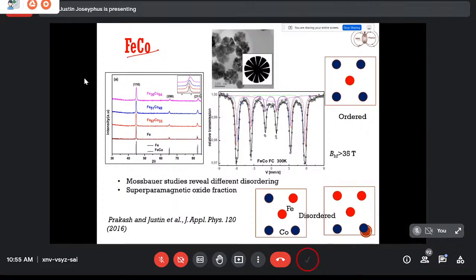And you see here, this is the X-ray diffraction pattern. XRD can be used to find the crystal structure. For iron, this is a body-centered cubic crystal structure from X-ray diffraction. You can see 110, 200, 211 peaks. And for the iron cobalt also, you can see that there are no impurity phases. You are not seeing any iron oxide. Iron oxide will come around here. The peak can be easily found. Okay. So from this, we have seen that we can prepare pure iron cobalt using the polyol process.